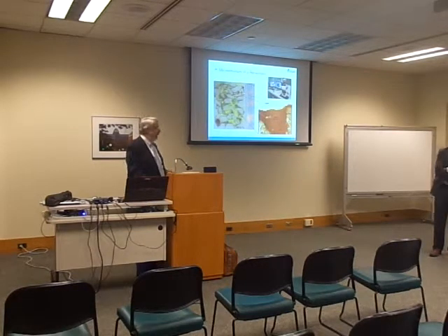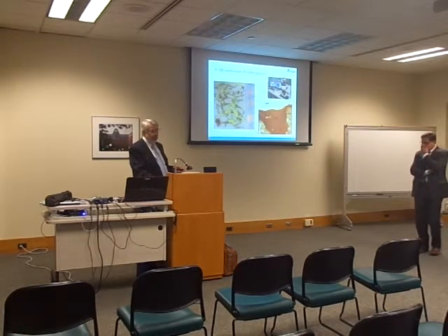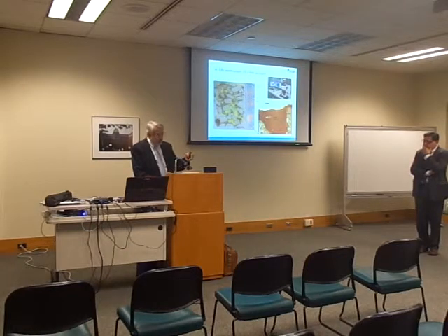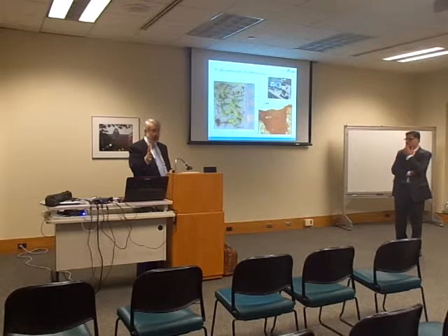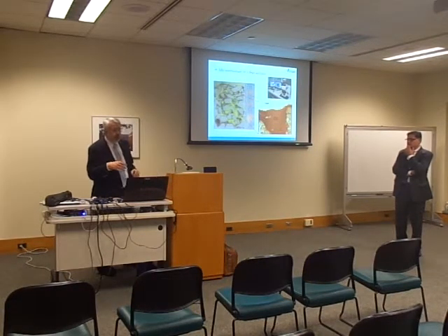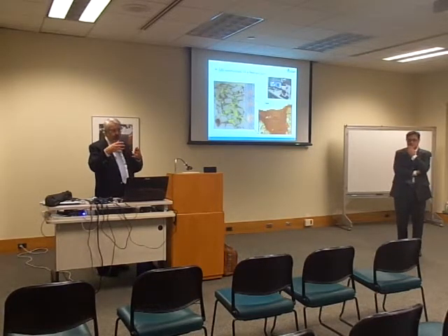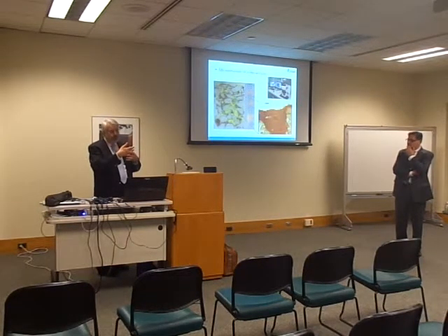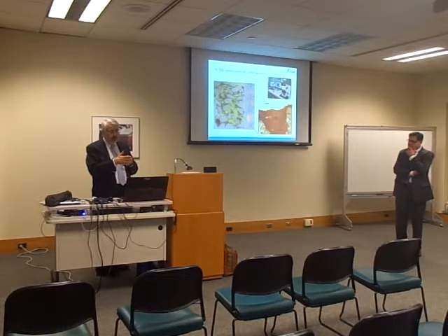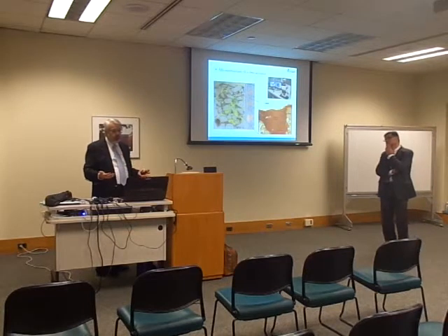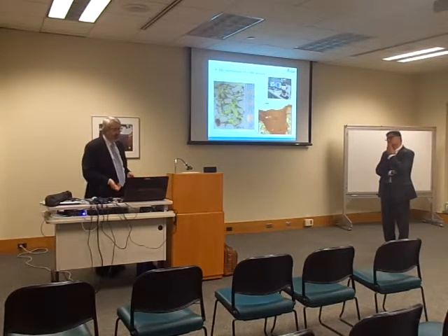I hope that indeed the rejuvenator goes towards the stone, to the interface, because that's another world out there, which also can fail, which also degrades, which probably also starts degraded because of depletion phenomena. Depletion is when some of the goodies of bitumen get into the porous structure of the aggregate and leave behind the bigger ones, the stiff ones. So that interface is a bad area. I cannot easily get to it though. I have to go through the bitumen. So we said, okay, let's try the bitumen first. I don't know if that answers your question.